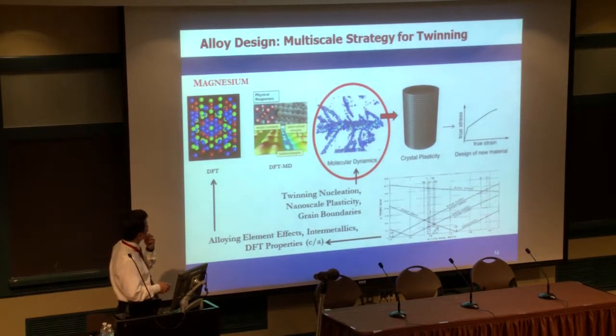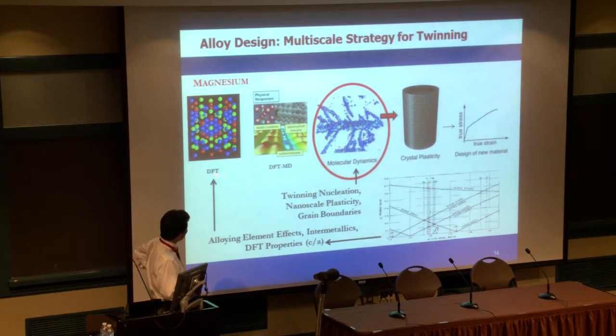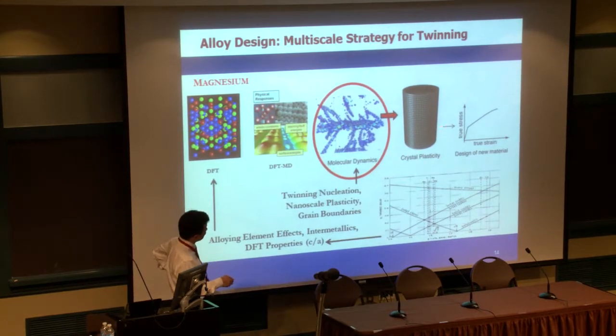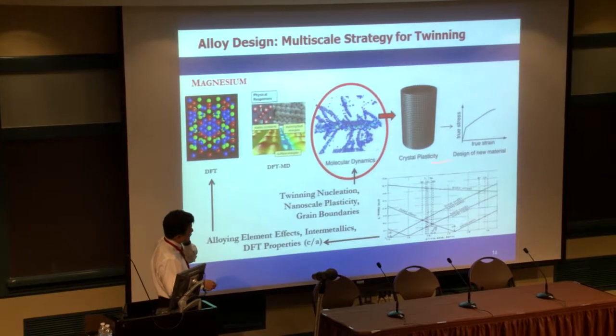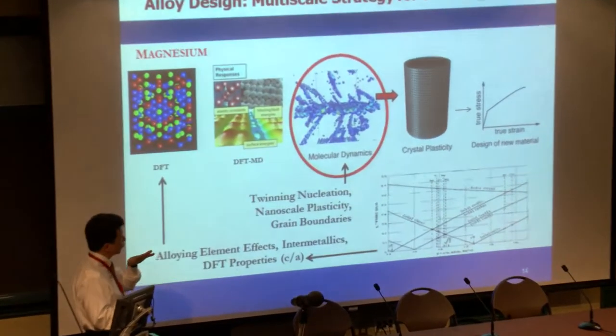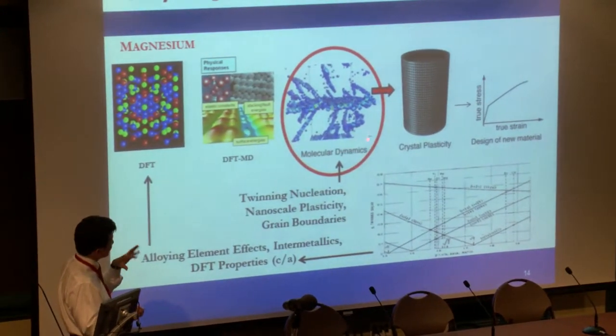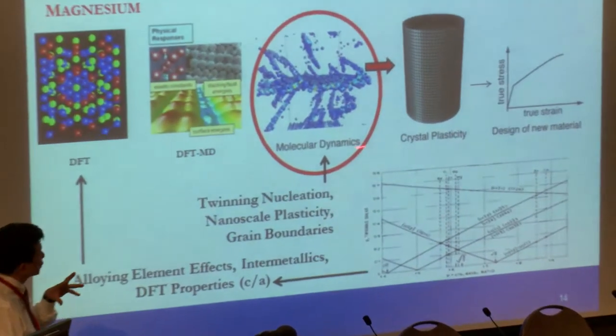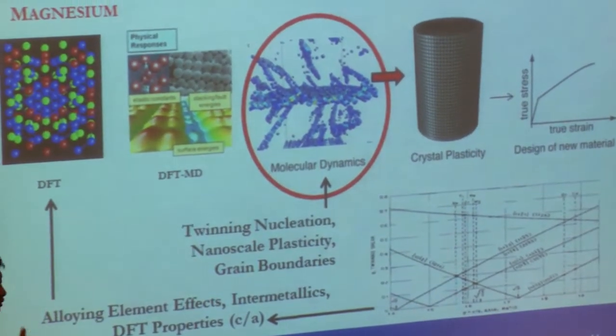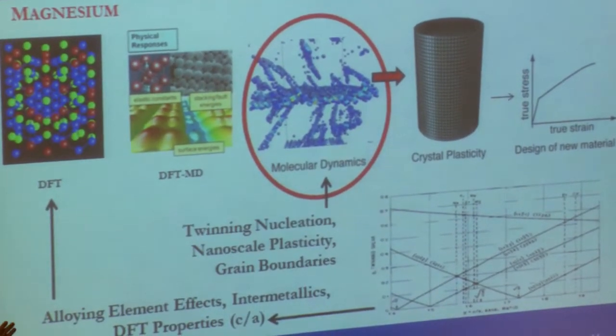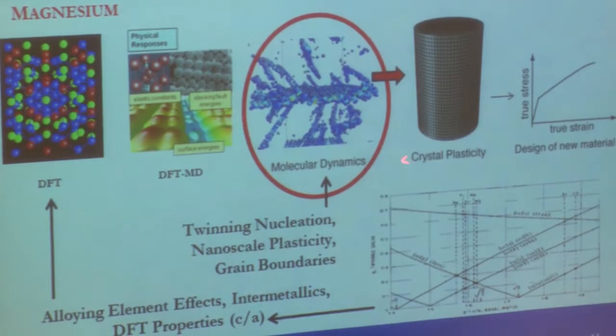And our optimal goal actually is looking from this area, look into the DFT in the molecular dynamics, and look into the grain boundaries, and eventually crystal plasticity and stress strain curve. We did have some success of pure aluminum, and also we have some success on pure magnesium. So the rest of it is working on the intermetallic and soluble phases and see whether these things can come out easily.